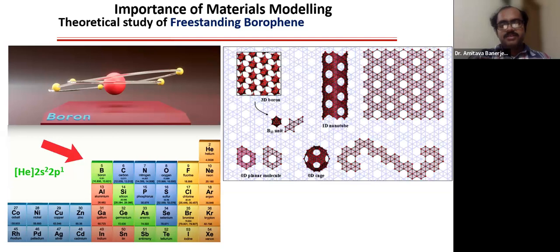But its orbital radius is very close to the 2s state, which makes it sufficiently localized to allow for the appearance of non-metallicity. So you have two different characteristics, metallic as well as non-metallic, in the same material, which you can tune. Such a unique electronic structure of boron enables the formation of highly diverse bonding in the bulk phases, ranging from strongly covalent two-center bonds to metallic-like multi-center bonds. These multi-center bonds are responsible for forming the polyhedra.